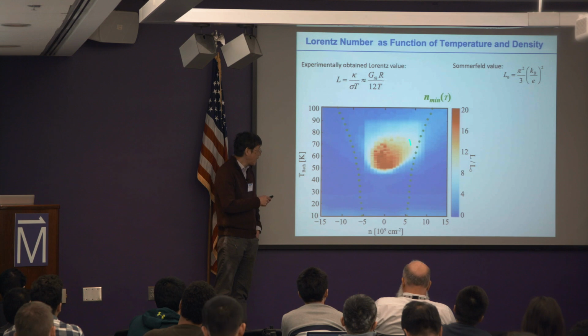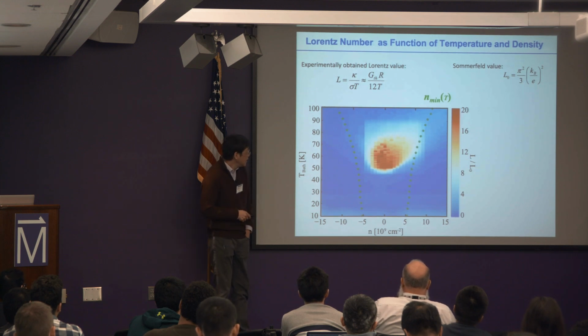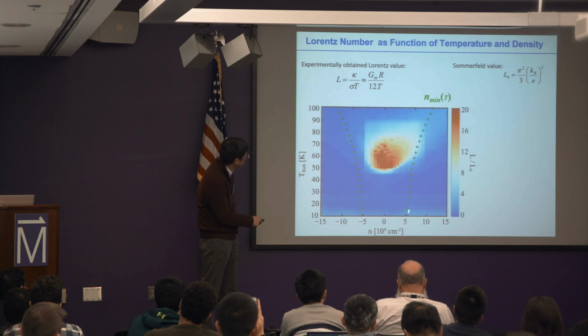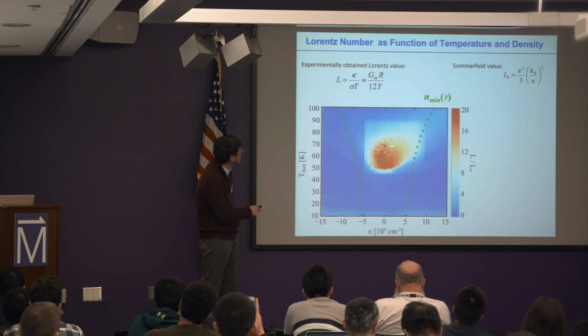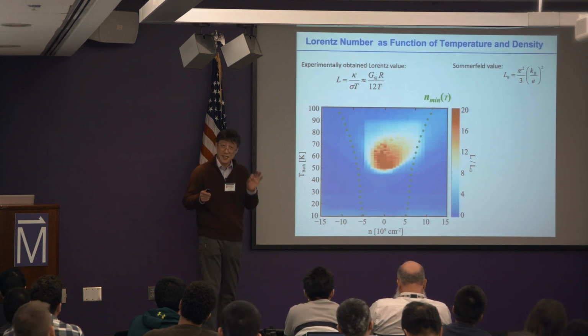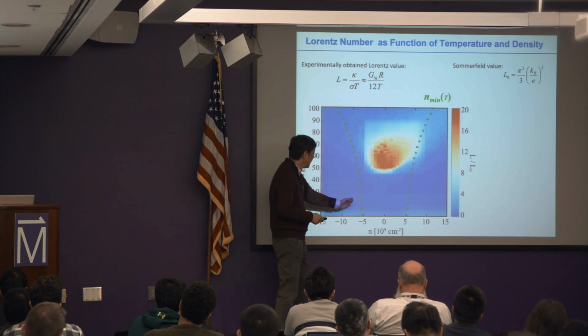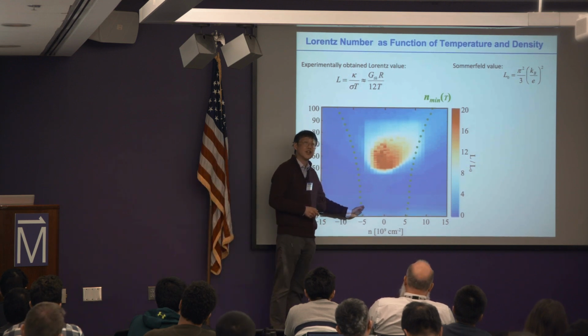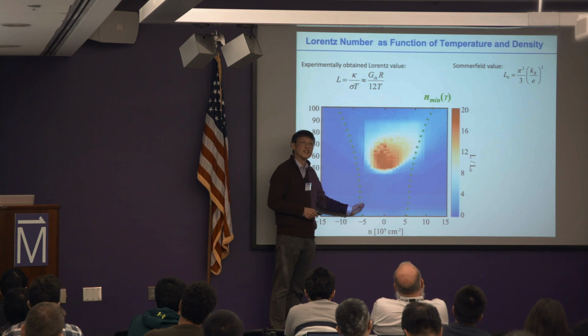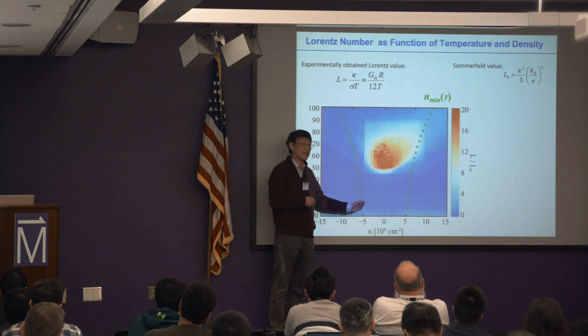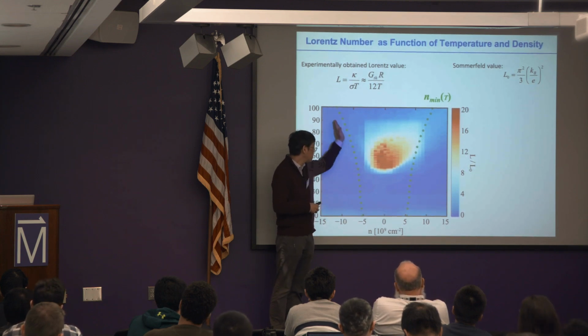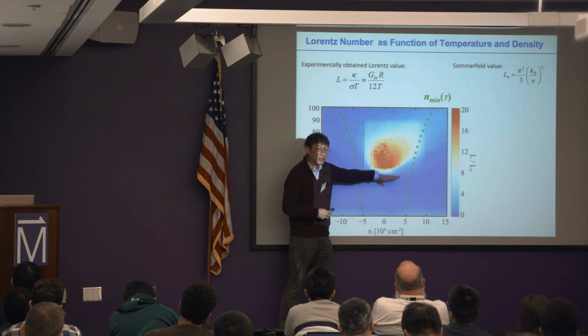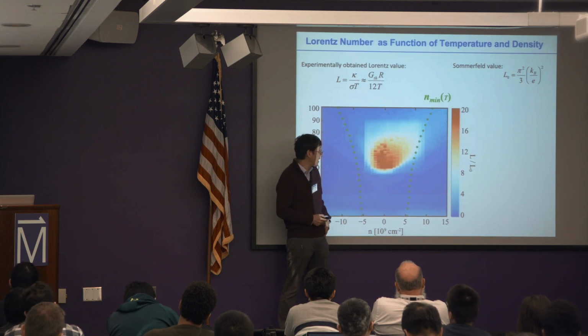Can I explain why there is a deviation like this? First of all, note that I plotted this green dot, which is basically the trace of the minimum of the density. This is a point I extracted where conductance does not change much with density changes, but then conductance starts changing with density and temperature. And this is the point where disorder and thermal broadening are happening.